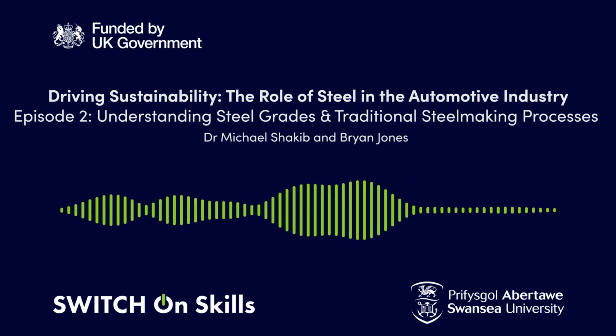And the final grade of scrap that's available is that from, say, automotive manufacture. So typically, you put a ton of steel into an automotive factory, and half of that ends up as scrap at the end of the day. And that is then scrap of known composition. So you'll have different bins of scrap for, say, high-strength steel or a dual-phase steel. And that can be sold back to a scrap merchant who can demand a much higher price for the product because it's of known chemical composition. So that sort of product would be ideal for automotive. Unfortunately, as I mentioned, 3/4 of the scrap available worldwide is merchant scrap, where there's limited knowledge of its chemical composition.